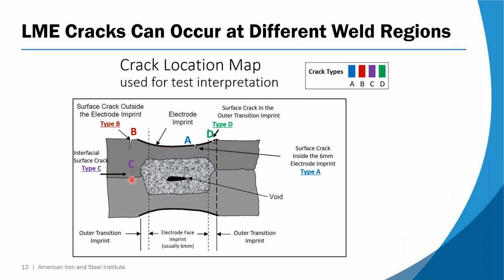Okay, and then type C is when it cracks in between the sheets. This is reasonably rare, but maybe it's rare because it's hard to find, because it's not visible unless you actually section the sample and get lucky. That's when we've seen it. You could x-ray it, maybe find it that way, but anyway, in this particular spot weld test, we don't see C very often.